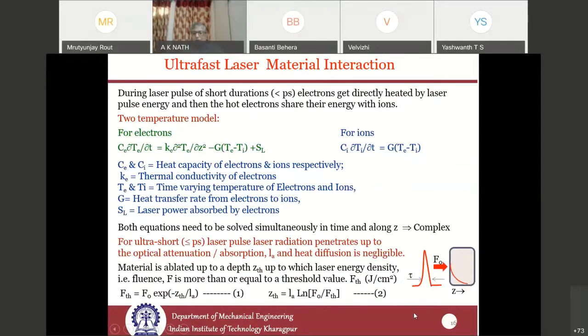Here, our assumption is that the laser intensity is absorbed at the surface and up to a depth governed by the optical skin depth, or attenuation length.